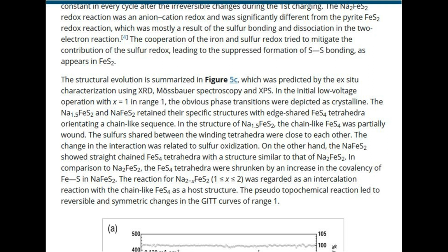as crystalline. The Na1.5FeS2 and NaFeS2 retained their specific structures with edge-shared FeS4 tetrahedra orientating a chain-like sequence. In the structure of Na1.5FeS2, the chain-like FeS4 was partially wound. The sulfurs shared between the winding tetrahedra were close to each other. The change in the interaction was related to sulfur oxidization. On the other hand, the NaFeS2 showed straight-chained FeS4 tetrahedra with a structure similar to that of Na2FeS2. In comparison to Na2FeS2, the FeS4 tetrahedra were shrunken by an increase in the covalency of Fe-S in NaFeS2.